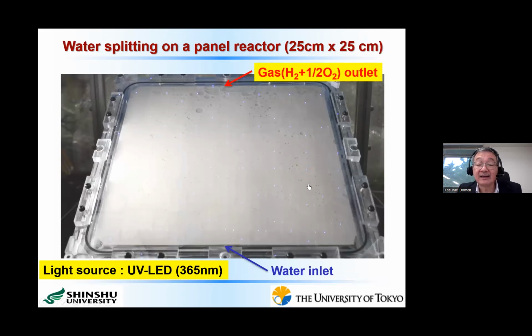Then this is an experiment using such a system. In this case, we use a UV LED at 365 nanometers to irradiate this water splitting panel. I hope that you can see a small bubble is formed and going up, then going outside through the gas outlet. I should say that the efficiency of the water splitting reaction in this case is exactly the same as when we have a millimeter or a centimeter thickness of water layer. That means that a 100 micrometer distilled water layer is enough to be effectively split by the photocatalyst.